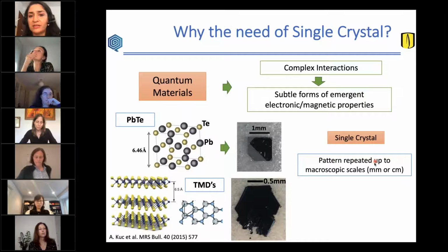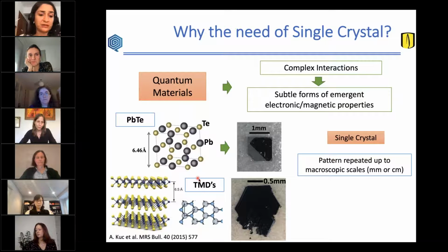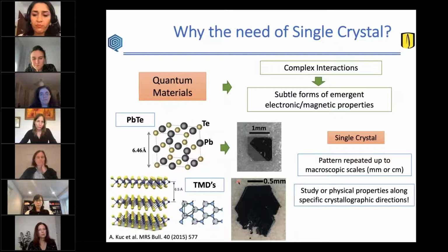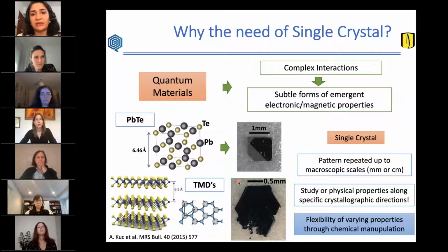So currently we are studying different compounds. Lately we've been focusing on some transition metal chalcogenides. This is an example of a 2D transition metal dichalcogenide in which we are able to grow and synthesize very nice and large single crystals in which this macroscopic shape is a reflection of these beautiful unit cells that can be exfoliated down to one monolayer. All right, so our expertise in producing these single crystals allows us to have the flexibility of varying these electronic properties with chemical doping and optimizing and strengthening some of the novel phases we want to focus on.